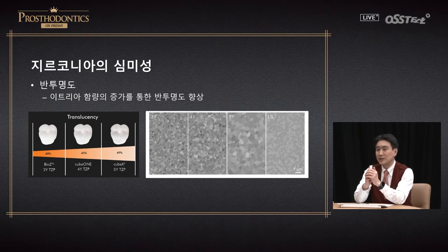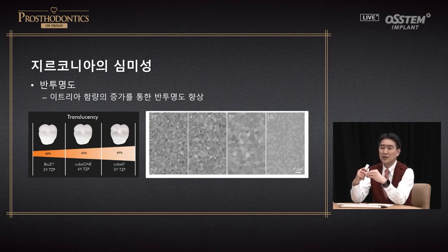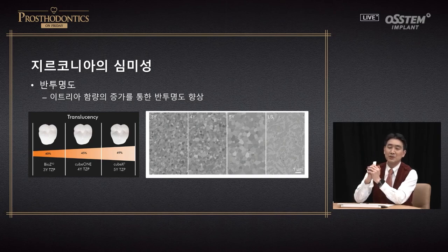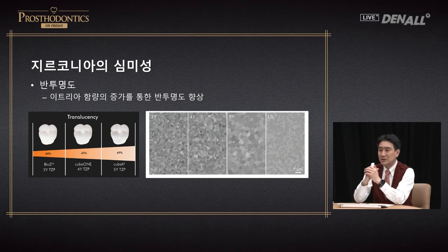Zirconia with 5 mole yttria, if you look at the grain size under the microscope, it has increased. And what's in it is the clear cubic phase. So overall translucency and transparency has improved. The cubic phase is above tetragonal phase. The benefit of zirconia transformation toughening does not exist in cubic phase. If you use cubic phase, you forego the benefit of zirconia, so it is brittle and has less hardness. As a result, you need to understand that you're losing some of the benefit of zirconia when you use zirconia with high yttria content.